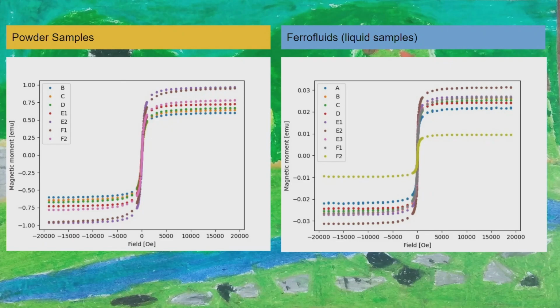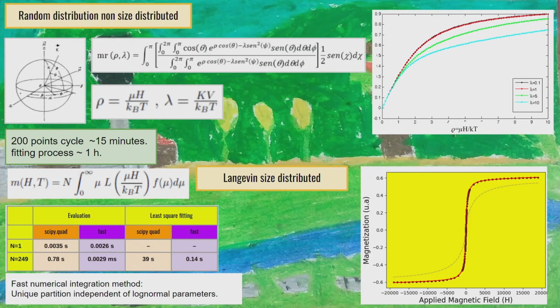We also characterized the samples by magnetometry at room temperature, powder samples and liquid samples as ferrofluid. Random or powder samples can be analyzed, or must be analyzed, with a random magnetic model, a random distribution of anisotropies. And in the case of ferrofluid, it can be analyzed with a free-to-rotate distribution of Langevins. Sorry, because of the English.